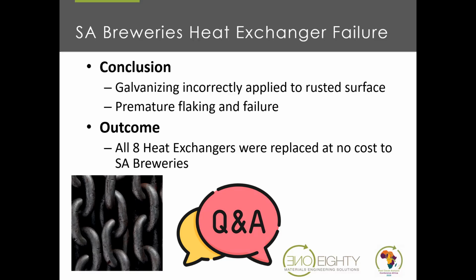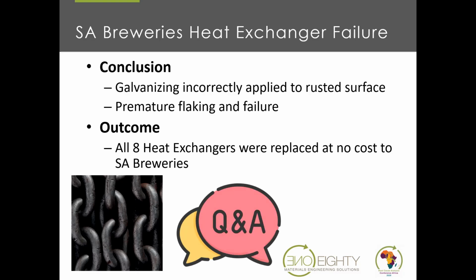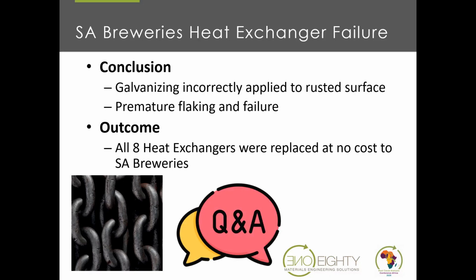Yes, Andrew. What exactly does the acid do to the rust when you wash? You said you wash off the rust. Yeah, it will dissolve the iron oxide. Does it create a coating? No. It just dissolves the iron oxide and even takes a layer of the steel or strips a layer of the steel so that the steel is completely pure iron without any contamination. And it's rinsed and goes immediately into the bath.